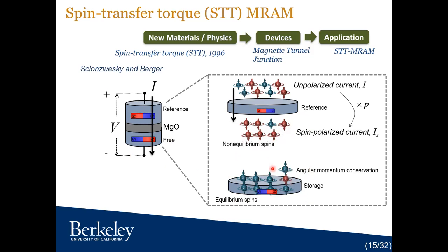So one non-equilibrium spin comes, hits one of the equilibrium spins, and there will be an angular momentum conservation. So now this one will become upspin and this one will become downspin. And if you hit the storage magnet with more spins, you will flip more of the spins inside the magnet. And these electrons then go away to the other terminal of the battery. And if you keep hitting your storage magnet with more spin polarized current, at some threshold value, you can switch it. So that's the basic of the spin transfer torque.